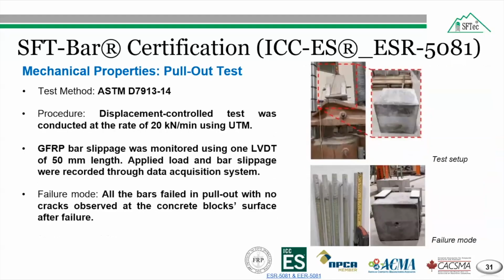So a displacement control test was conducted at the rate of 20 kilonewton per minute using the universal testing machine. And the GFRP bar slippage was monitored using one linear variable displacement transducer. And the applied load and the bar slippage were recorded automatically throughout the test with a computerized data acquisition system. So all the bars failed in pull-out failure with no cracks observed at the concrete block surface after the failure.